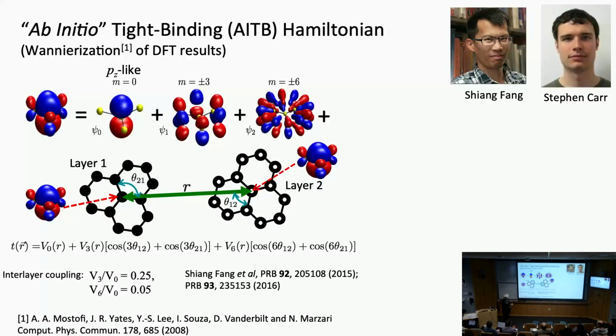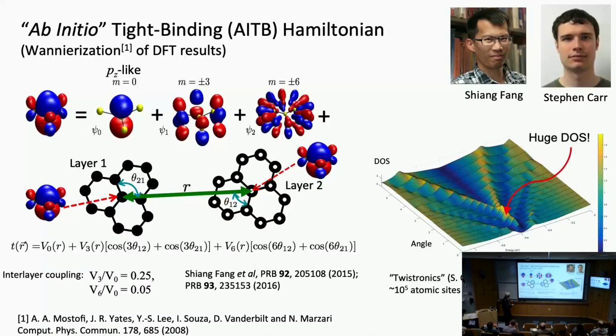So this is what the local basis looks like, and it consists of a pz orbital. So this is at the atomic level now, at the atomic scale, and higher orbital momentum contributions. And when you take these kinds of localized states at each atomic position, and you include their interaction, as we can compute it from theory, you produce this kind of diagram, which is now the density of states on the vertical axis as a function of twist angle on this axis and the energy on this axis. At no twist, you have two layers, and there's a minimum here in the density of states. So this is the position of the Fermi energy.